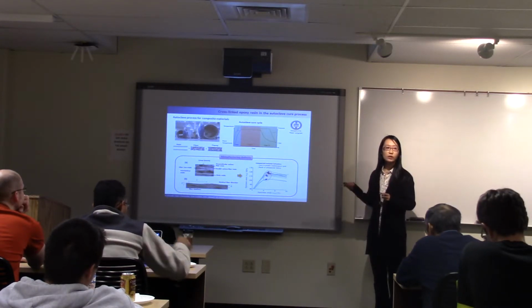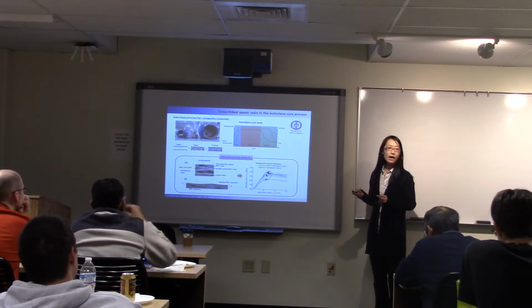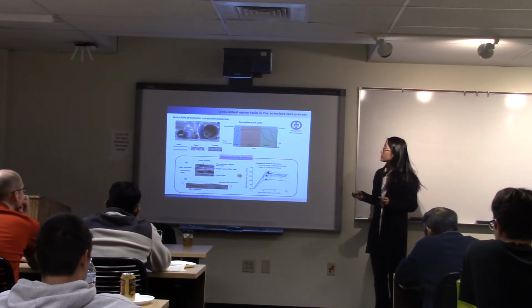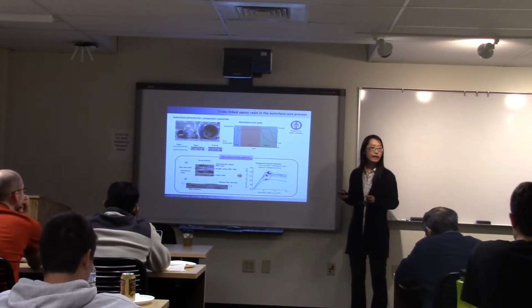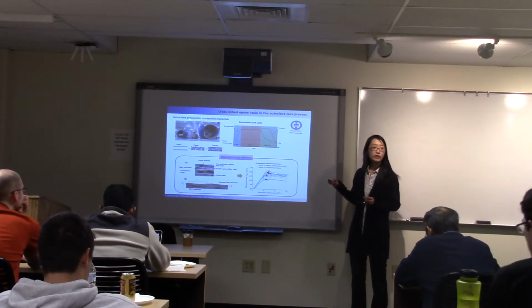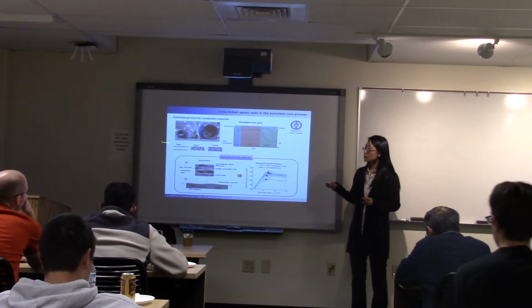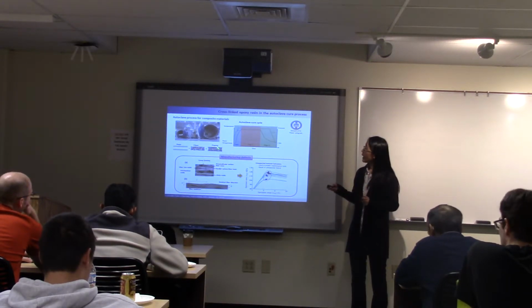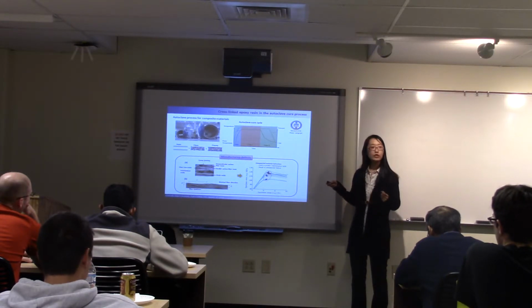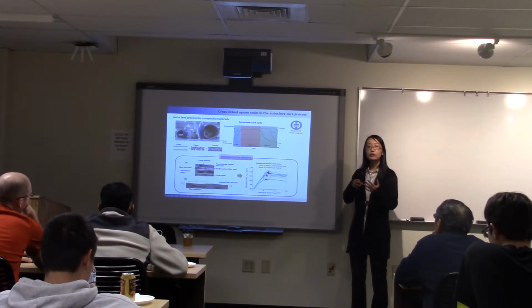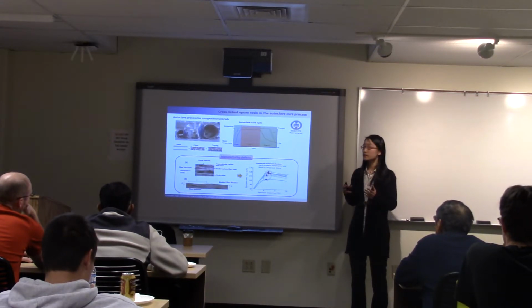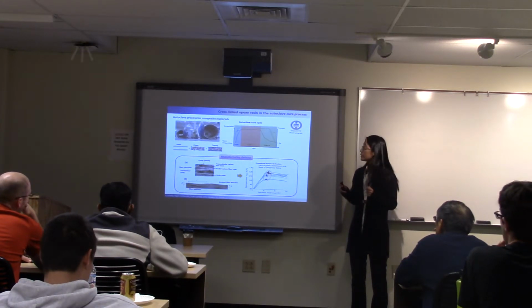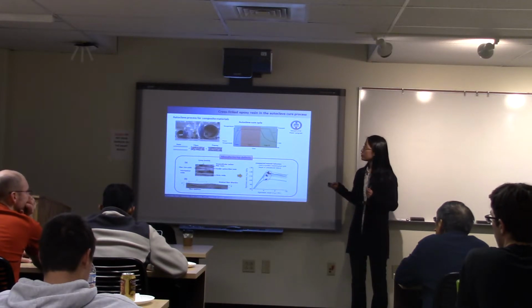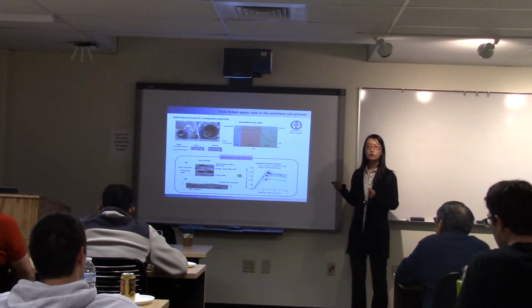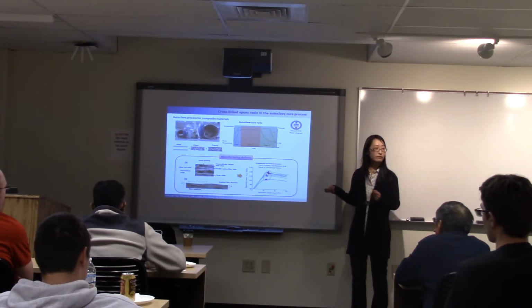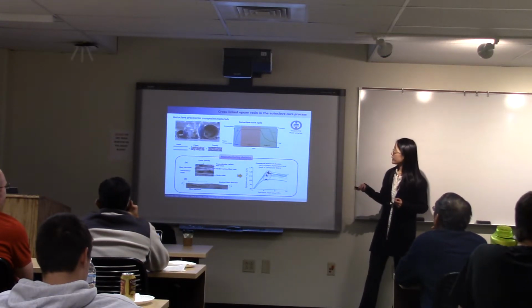So the objective of this project is to predict the manufacturing defects happening in the autoclave process for composite materials. The thermoset epoxy resin is commonly used as the polymer matrix for composite materials in DOD usage. This epoxy resin is mixed with the fiber to make the prepreg, and during the autoclave process the temperature as well as the pressure are increased. The curing process could happen, which would affect the thermomechanical properties of the epoxy resin. So we need to capture or predict those thermomechanical changes during this curing process with pressure, time, as well as curing degree, in order to predict the manufacturing defects, which could lead to unexpected material behaviors.